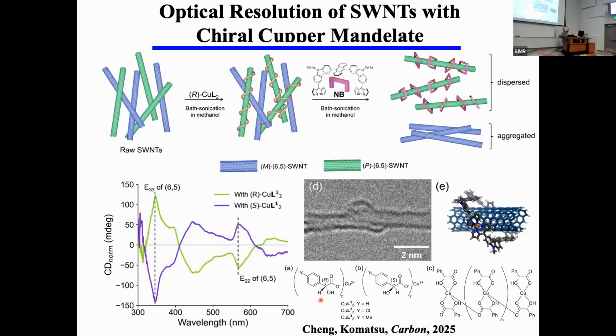Finally, we can interlock, and we can disperse or extract selectively the interlocked carbon nanotube with the specific handedness. This is our strategy to separate the carbon nanotube with the left-handed and the right-handed structures.